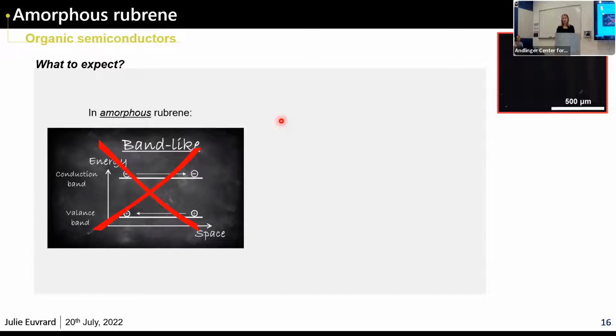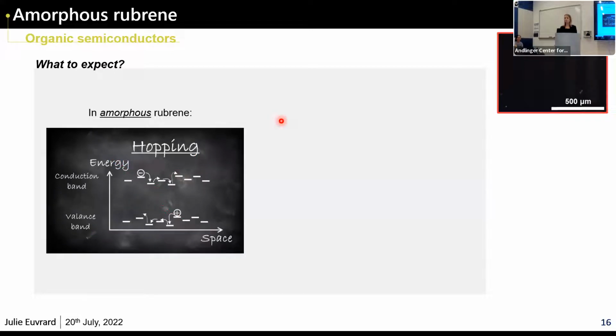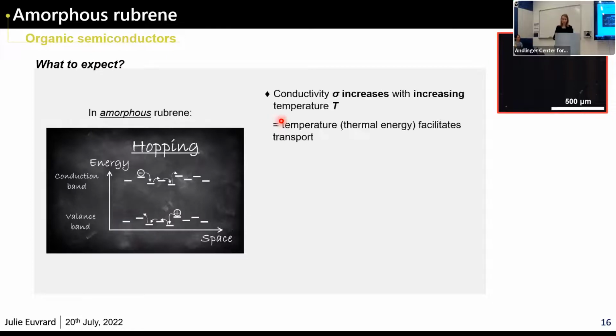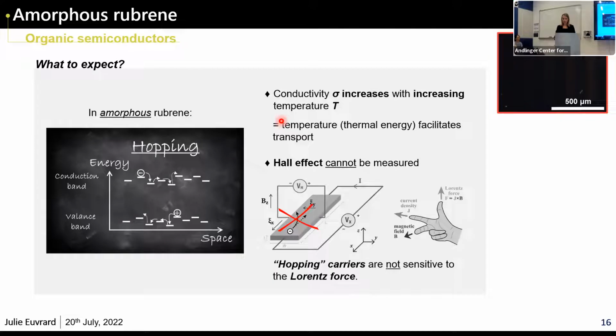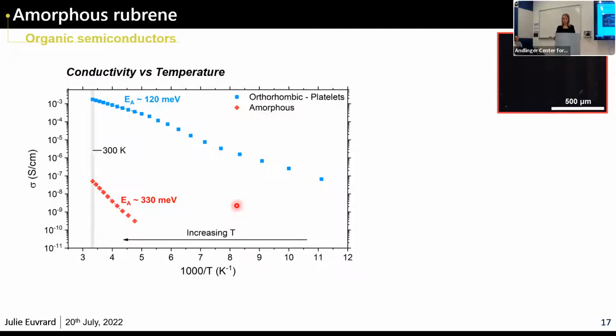In that case, band-like doesn't hold anymore. What you need to consider is hopping transport. So what is hopping transport? It's when you have a charge that is sitting on a molecule, and to travel around, it has to hop from one molecule to the next. And for that to happen, you need to provide energy. And so typically what you will have in that case is a conductivity that increases with increasing temperature. So by providing thermal energy, you make transport more efficient. But an interesting thing is that those hopping carriers do not feel the Lorentz force, which means that if you had pure hopping, no band-like whatsoever, you shouldn't have any Hall signal at all. So let's see if that's what we have.